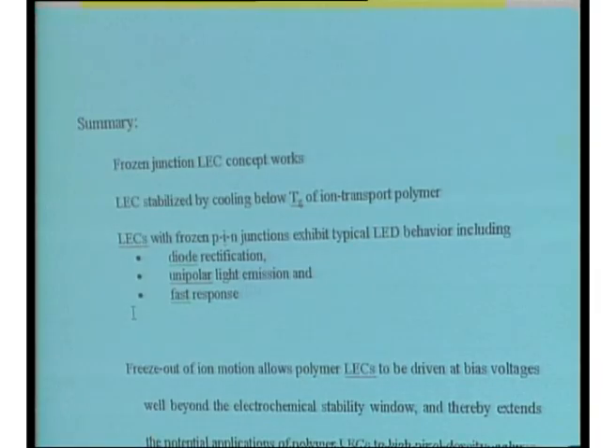The room temperature operating LEC is very interesting. We learned a lot, but the lifetime of the device is just not even close to what we can get in LEDs, and that's why what I'll call the conventional polymer LED is what is being commercialized. It is possible, in fact, I expect that if we really pursued the frozen junction approach, we could get long lifetime in the LECs, because the important thing is that once you have turned off the electrochemistry, then the side reactions are less probable and you probably get a longer lifetime.